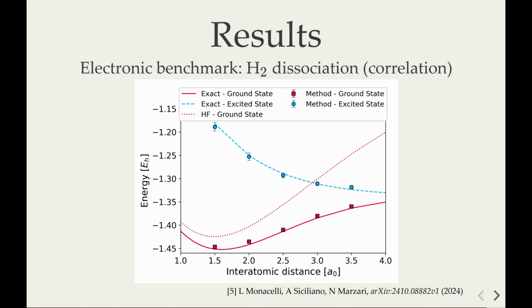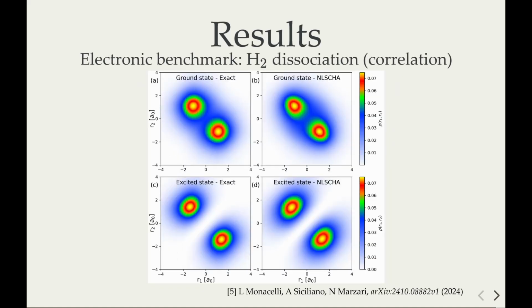Also excited states - in this case it's very simple because it's a different symmetry, so we can minimize the energy quite easily, and we get a very good result there too. This is restricting the spin symmetry to be satisfied in this case. So this is how the wave function looks like: here the exact ground state in 2 different regions in dissociation, and here is our ground state.